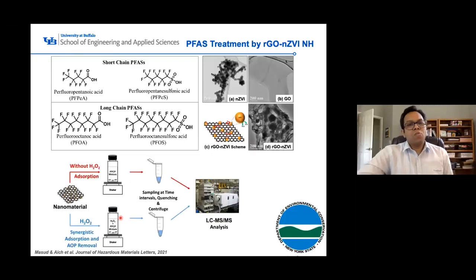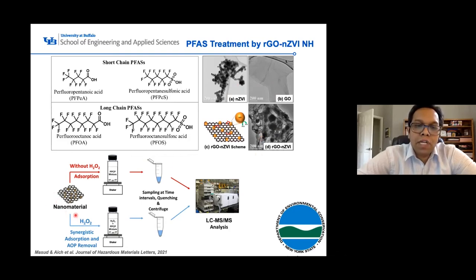Okay, so we took four different PFASs, two short chain, which are less than five carbon, and then two long chain, eight carbon chain PFASs, which are most well-known, PFOA and PFOS. We had these different nanomaterials, NZVI, graphene oxide, and rGO-nZVI. And we did two sorts of experiment. One is without hydrogen peroxide, which gives us mostly adsorption. So we put the PFAS solutions in water with the solid materials in them. And then same thing with hydrogen peroxide. After some time, we centrifuge them to remove the nanomaterials and then take the supernatants to run through the liquid chromatography mass spectroscopy to identify the PFASs that are present there or any degradation product.